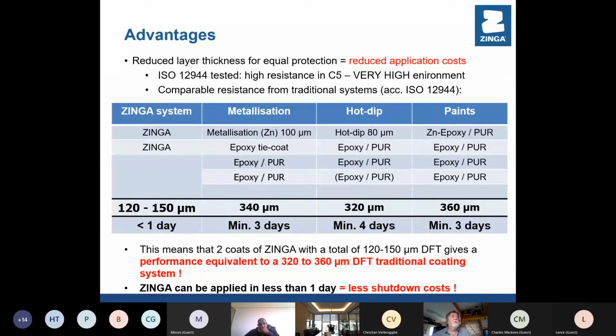Okay, here's a quick system to show you a comparison. Two layers of Zinga can be applied in one day. Well, in fact, it can be applied in 2 hours. And if you compare that to metallization, which is thermal zinc being sprayed on, it has to be sealed with a tie coat. It has to, or it'll be contaminated. Then it's top coated with a polyurethane. That's a minimum of a 3-day system because the epoxy takes 24 hours to cure. With hot dip galvanizing, again, it's minimum 4 days because each layer of epoxy has to cure overnight before you can apply the next coating. And then the zinc epoxy with polyurethanes, again, is a multi-layer system. And again, it's a minimum 3 days.